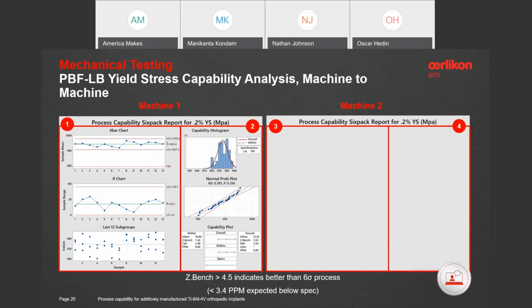So we plotted the histogram and also included our specification limits. Here, the specification limits are slightly different than ASTM F2924. They're actually lower. So the specification limit here is 795 megapascals for the yield strength. So once we put in our specification limits, we have a CPK value and PPK value greater than 1.33. And also the z-scores are greater than 4.5, which indicates that the process is achieving a Six Sigma level.